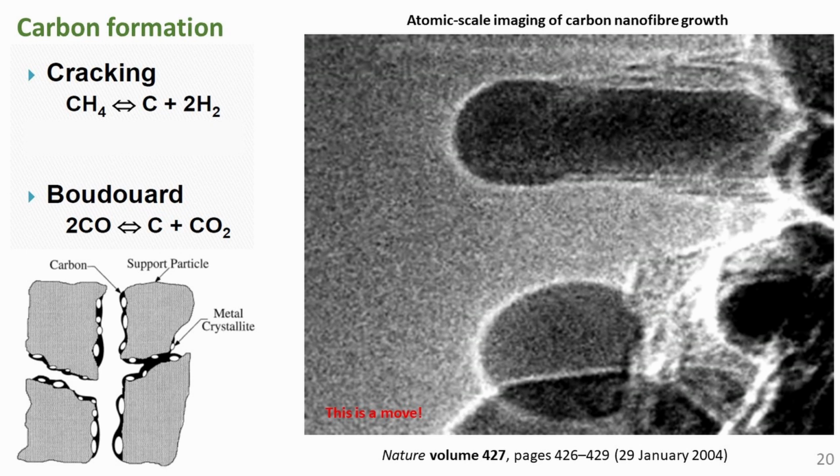In situ high resolution transmission electron microscopy demonstrated that the process of carbon formation is very dynamic, involving drastic changes in the nickel crystal during the nucleation. It has also been possible to observe how the graphene layers grow from surface steps which are created during the nucleation and which move as the graphene layers grow. This is illustrated in a figure.